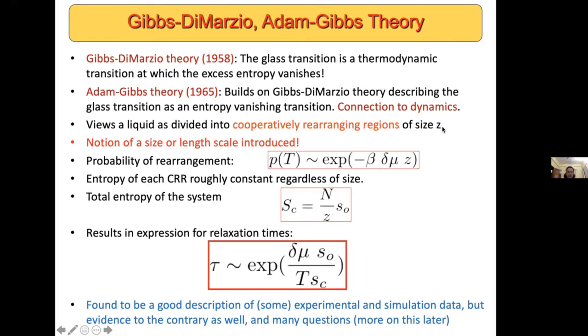relaxation to occur. And so this is sort of the first point in the history of ideas about glassy behavior, where the notion of a relevant size or length scale is introduced. And Adam and Gibbs made the assumption that the probability of rearrangement would somehow depend exponentially simply on the size of these regions. So, and conversely, the typical time necessary for such structural reorganizations will grow exponentially with the size of these regions.